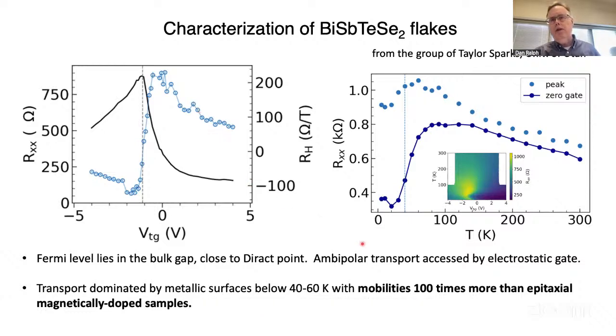And we've done these experiments with flakes of different quality, and you really need very high quality topological insulators to start with to see high temperature scales. The signatures of having a very high quality crystal are a sharp Dirac peak, just measuring the topological insulator flake by itself with no magnet, and then being able to gate through the Dirac point and seeing the ambipolar charge conductivity. So well-defined hole and electron transport on both sides of the Dirac point. With these flakes, you can also, even before you put magnets on, look at the longitudinal resistance as a function of temperature, and they're dominated by the surface states below about 50 or 60 Kelvin.